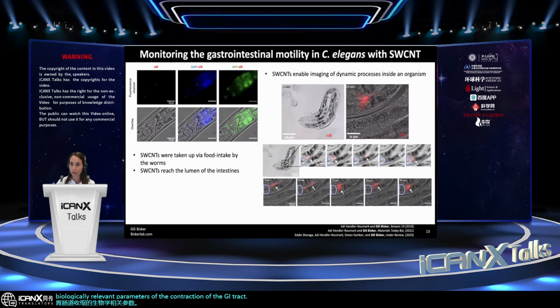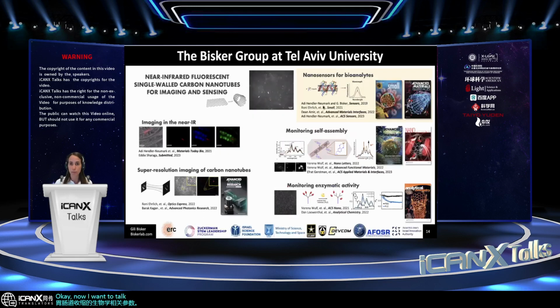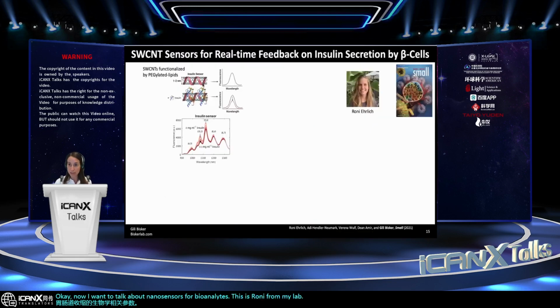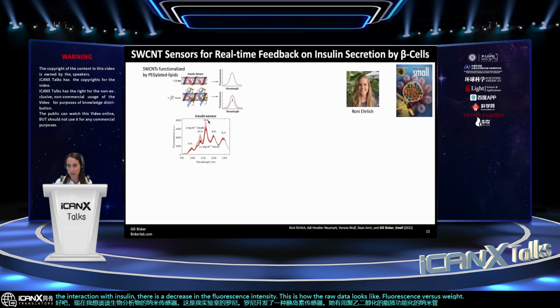Okay, now I want to talk about nanosensors for bioanalytes. This is Roni from my lab. Roni developed a sensor for insulin. She has nanotubes functionalized with pegylated lipids that upon the interaction with insulin, there is a decrease in the fluorescence intensity. This is how the raw data looks like. Fluorescence versus wavelength. The top curve is the initial fluorescence. As we increase the concentration of insulin, there is a gradual decrease in the intensity.